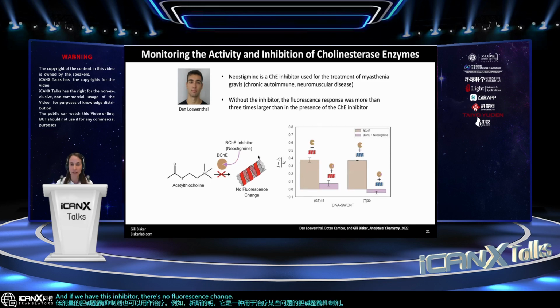This is the normalized fluorescent response for two different of our sensors, and you can see that without the inhibitor, the fluorescent response was more than 3 times larger than in the presence of cholinesterase inhibitor.